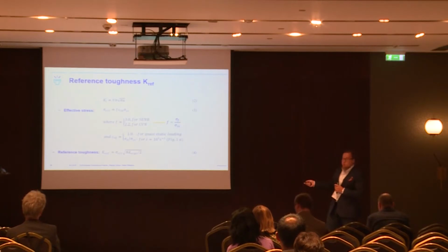So for cracked single-edge notch bend specimens, we have used 3.0, which matches with the small-scale yielding. Then for impact toughness specimens with a notch, we use 2.2, which is based on early analysis, Green and Hundy, and the other one that I forgot, but it also has a good match with the empirical findings from Bosset and others. And then, when we have quasi-static loading of fracture toughness test and dynamic fast loading in impact toughness test, we need to address the elevation in the yield strength due to this increase in the loading rate and strain rate. So this will be used in the function. I'll show you in the next slide.